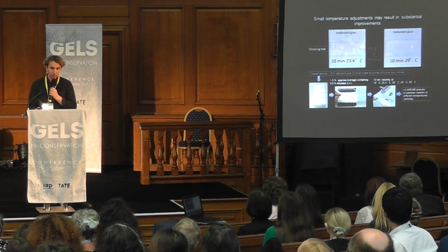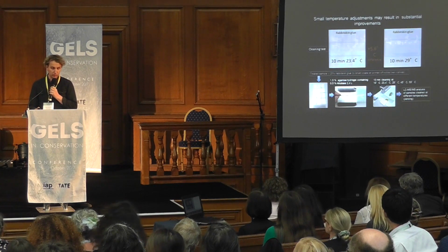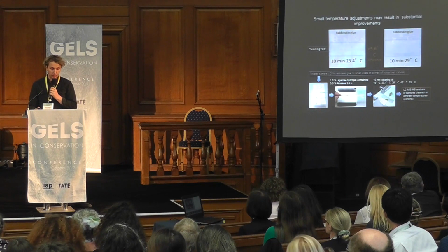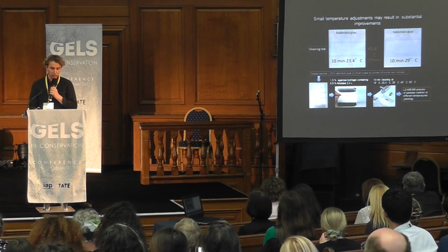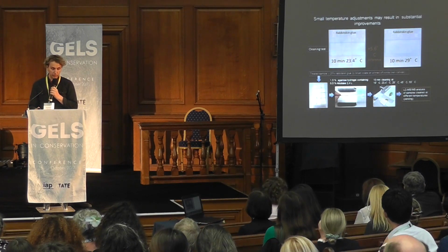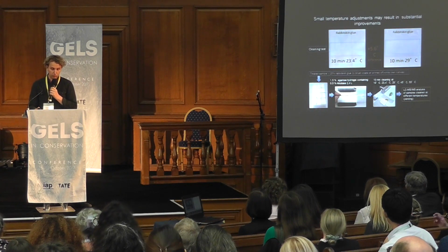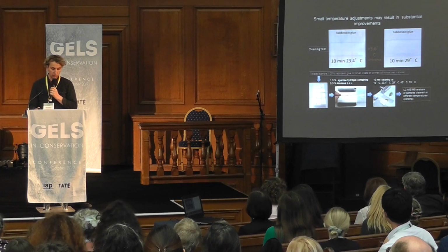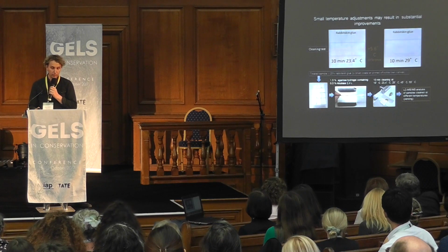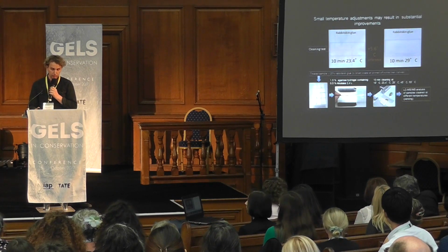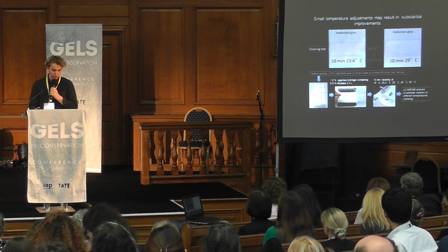Many enzymes simply do not work at ambient temperatures or are at best extremely slow. Therefore, heat transfer, even at a minimal rise of only a few degrees, may already radically improve the cleaning action, as the samples above demonstrate, where the rabbit skin glue was removed at 29 Celsius, but the hydrogel with the same concentration of enzyme was not effective at 23.5 Celsius.